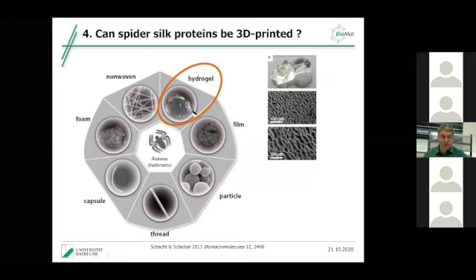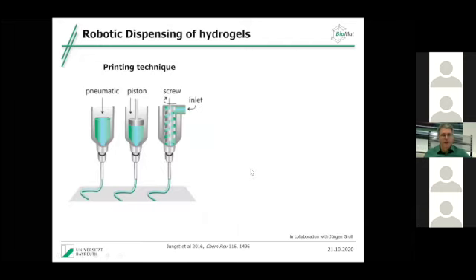And this has been shown almost 10 years ago, that we can make hydrogels out of spider silk. And this is just some SEM pictures to have a glance inside. And we see a porous structure, and the pores are fairly big enough to actually harbor human cells. So we thought these hydrogels are very well suited. The next step was, can we actually give these hydrogels also specific shapes?